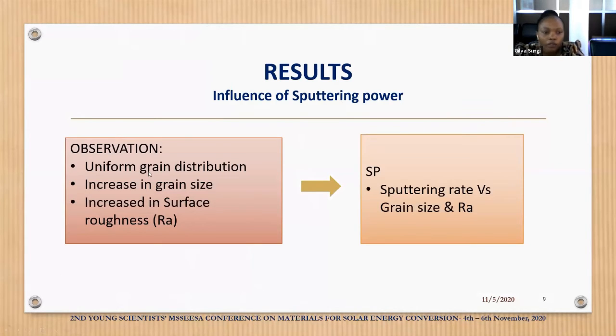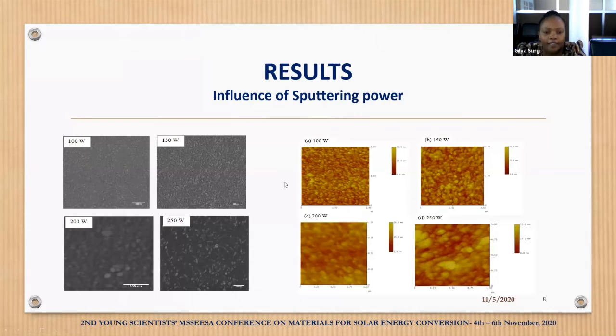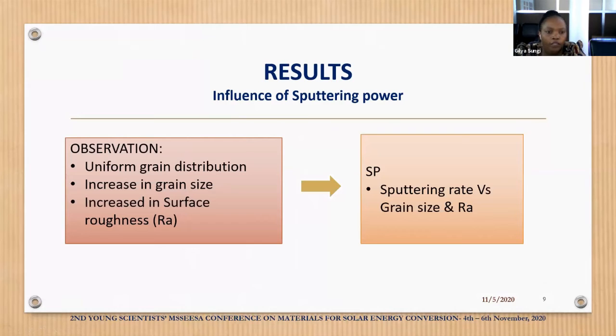So we have observed from the images uniform grain distribution, increase of grain size, and increase of surface roughness, which is contributed by the sputtering power, as the sputtering power increases, it will of course merge the quantity of grains, which results in bigger grains and surface roughness.